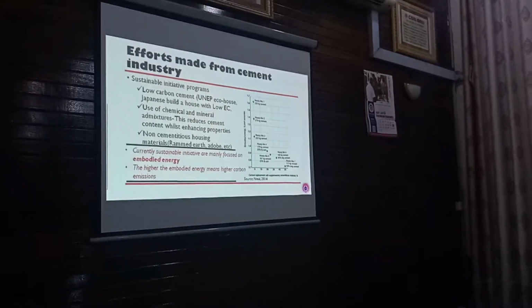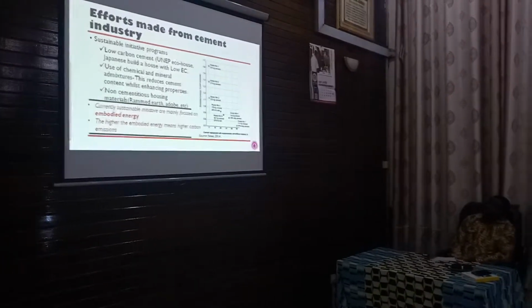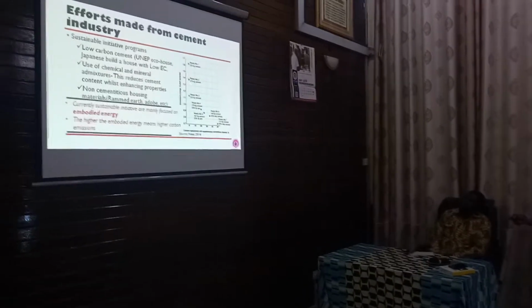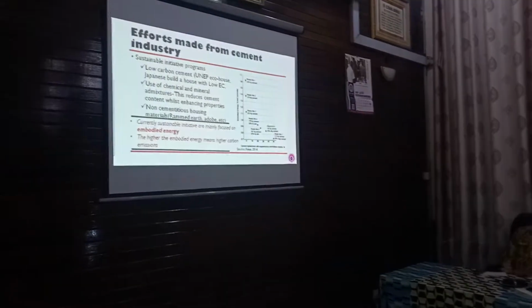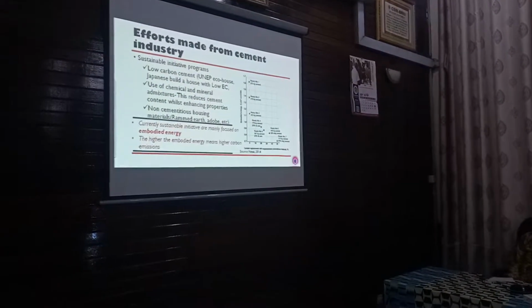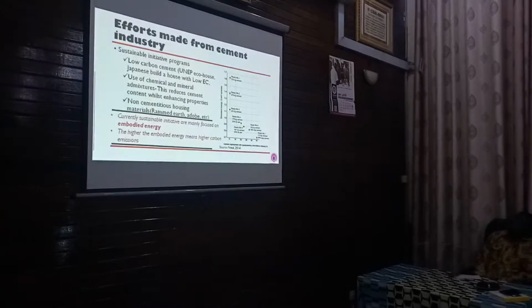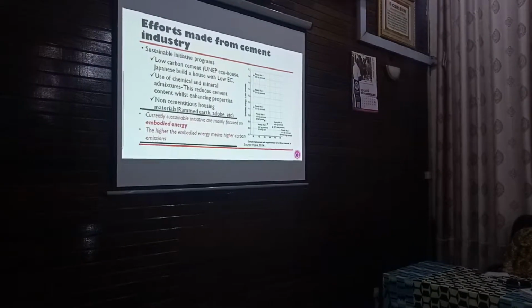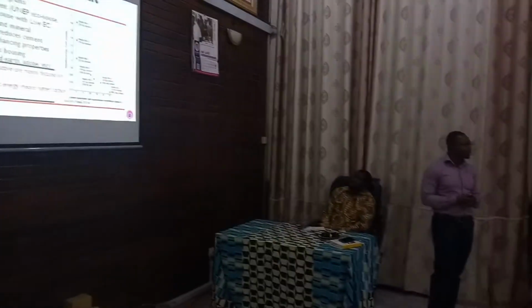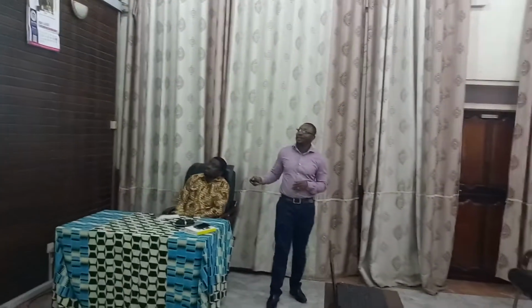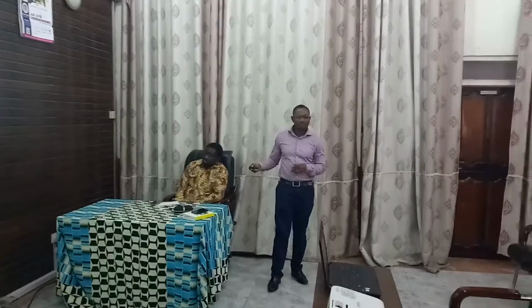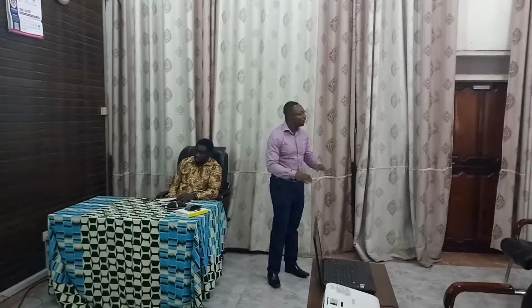Don't forget, I'm saying that embodied energy is related to carbon dioxide emission. So if you look at the graph, you can see that as the percentage of the replacement increases, the embodied energy decreases. For example, at 35%, you see that the embodied energy of the material is below even 0.9. So it means that if I use certain forms of mineral admixtures in concrete, I can bring down the carbon dioxide content. So that is the point.